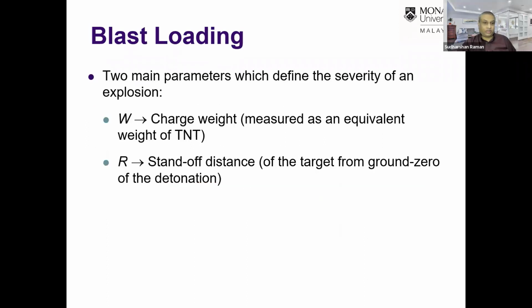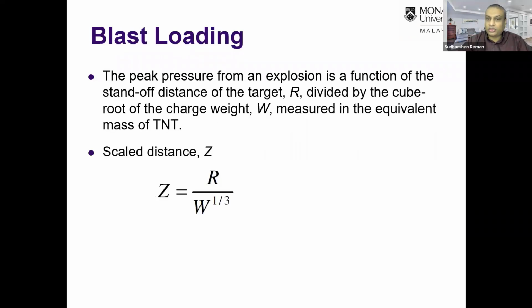In a blast load, there are two main parameters which define the severity of an explosion. The first one is the charge weight, and then the standoff distance. The charge weight is measured as an equivalent weight of TNT. Standoff distance refers to the distance from the explosive to the structure. The peak pressure from an explosion is a function of the standoff distance of the target, R, divided by the cube root of the charge weight, W, which is measured in the equivalent mass of TNT. This is called the scaled distance, and it defines the severity of a blast load.